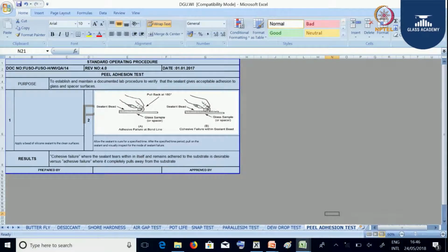Next we will see the silicone peel adhesion test. This is also one of the tests performed on the secondary sealant. We apply the sealant on a spacer and try to remove it. When the sealant completely comes out, you can say there is an adhesion failure between the secondary sealant and the spacer.